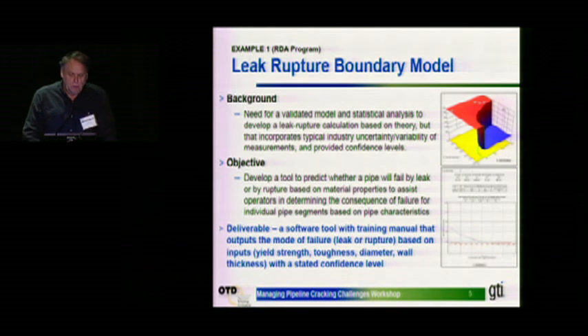So the tool will predict whether the pipe will fail by leak or by rupture based on the material properties and the pipe geometry, to assist the operator in determining the consequence of failure for individual pipe segments based on the pipe characteristics. So the deliverable is a software tool with a training manual that outputs a model of failure, the mode of failure, leak or rupture, based on the inputs, the yield strength, toughness, diameter, or wall thickness, with